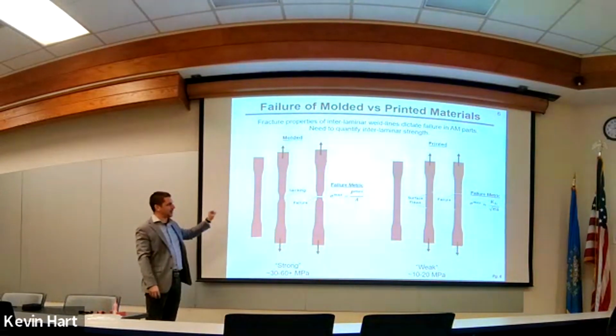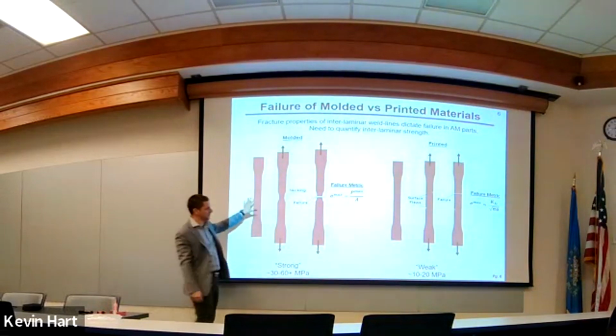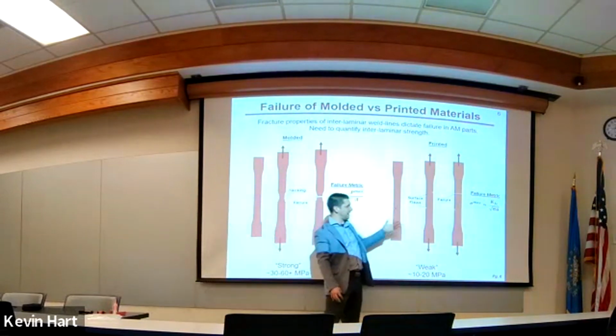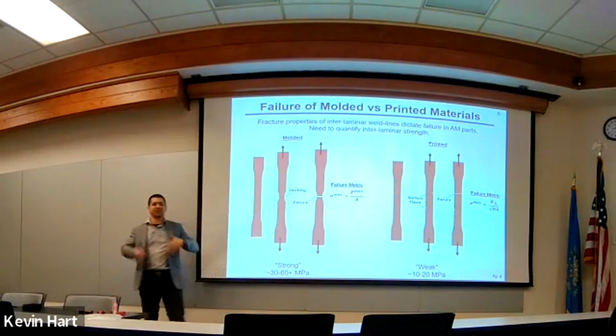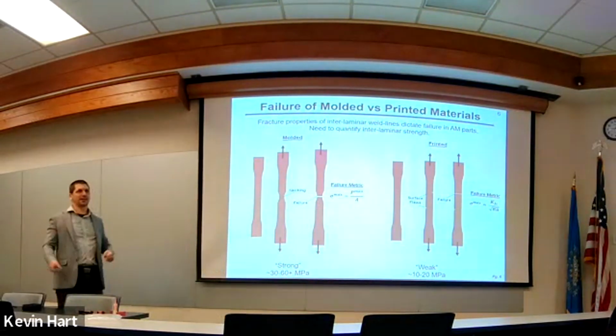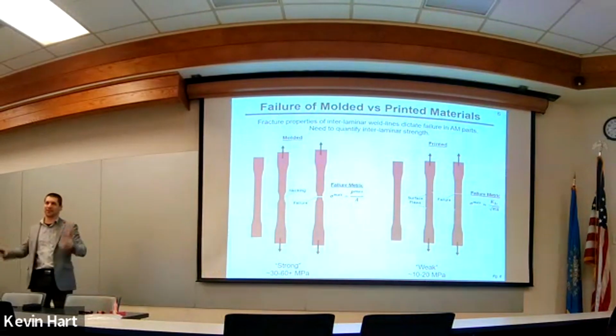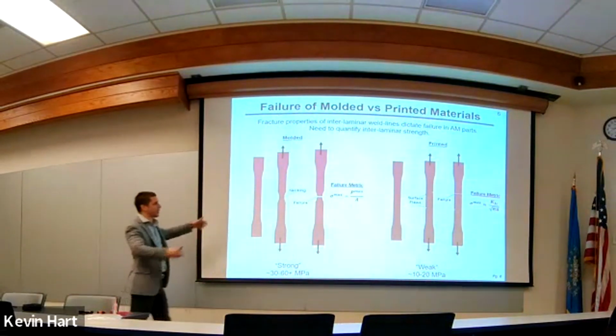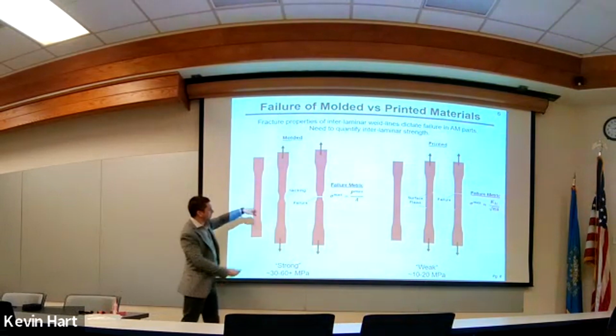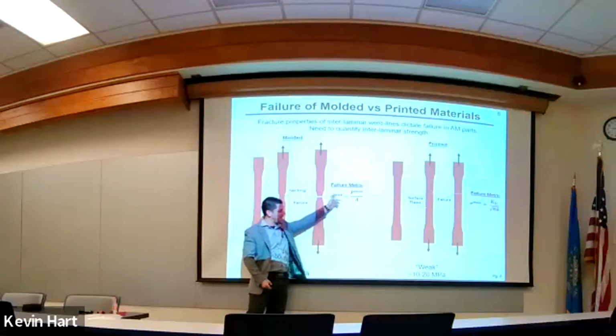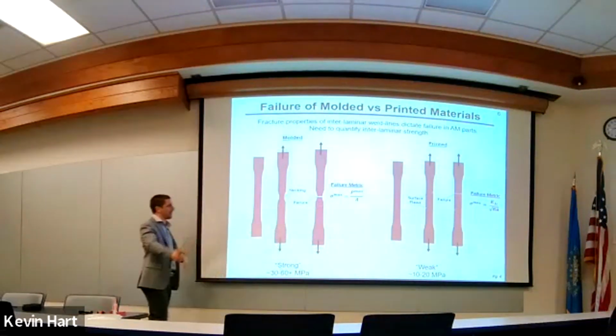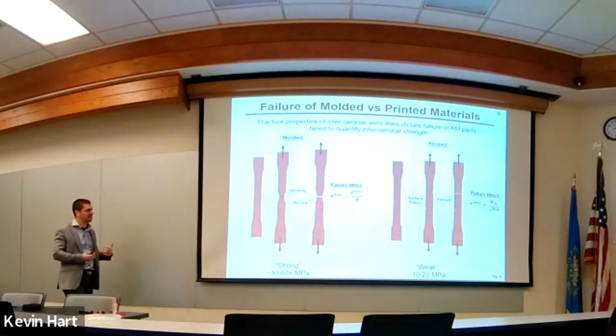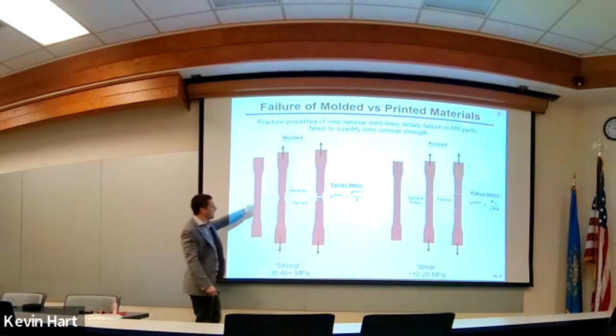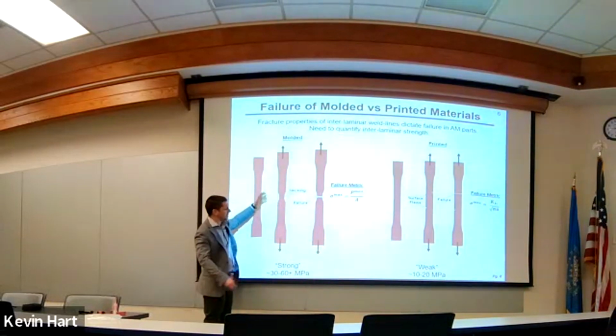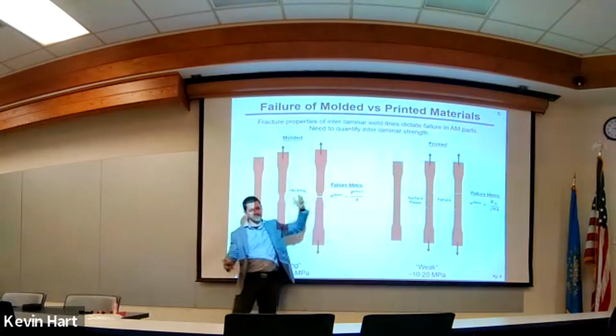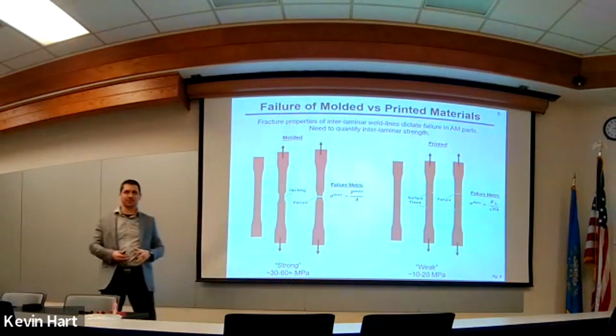And when I thought about this, I thought about, well, what is really the difference between something that might be injection molded that you test versus a 3D printed object that you might examine, all right? So if you've taken a strength of materials class, you've probably done something like, okay, this failure strength is the load divided by the cross-sectional area of the object. So you go to your lab class and you make these dog bones and you pull on them, and when you're investigating this stress to failure, you're taking the max load divided by the cross-sectional area. This is really investigating the strength of the material itself. So you'll see necking, if this is, let's call this ABS again, plastic. Ultimately, you'll see some necking probably if there's plasticity, and then it's going to fail, all right?